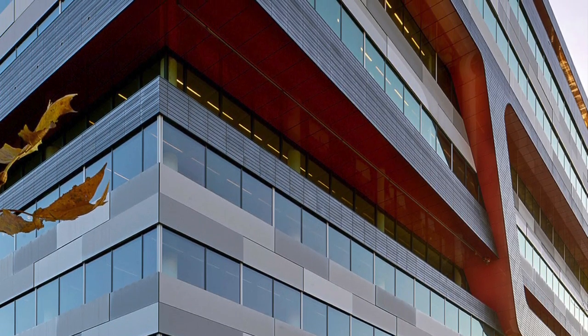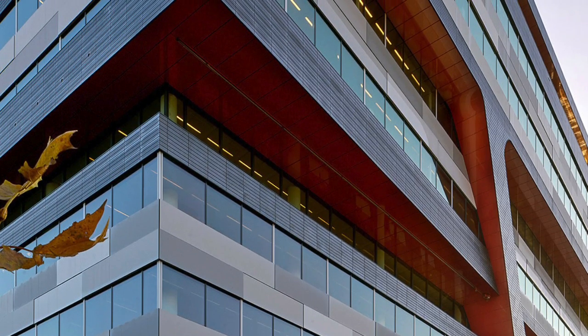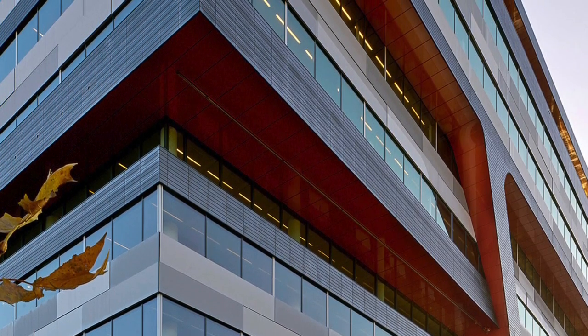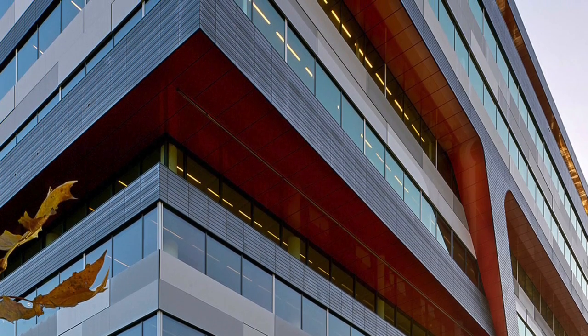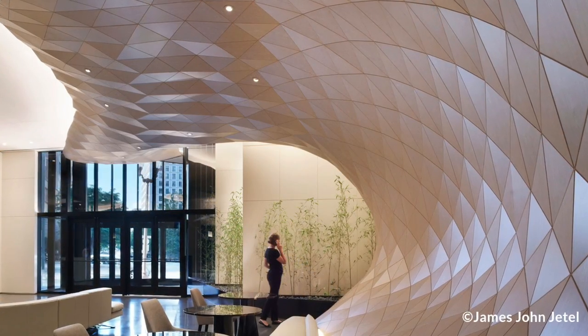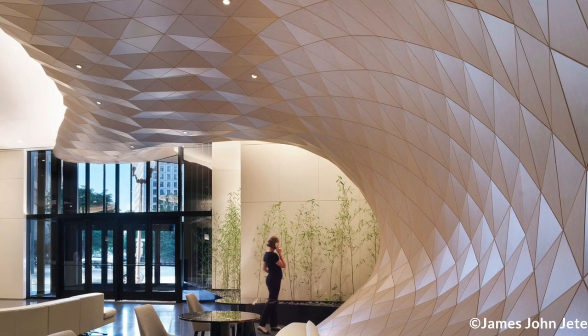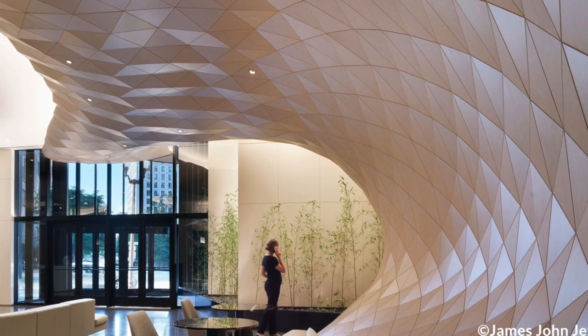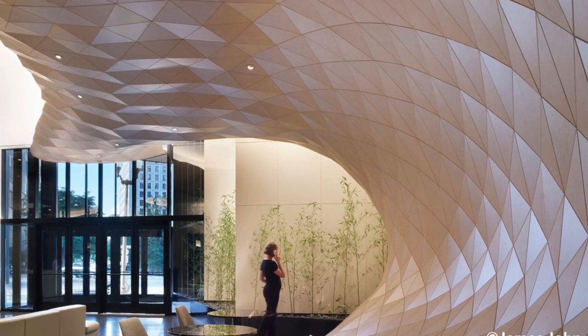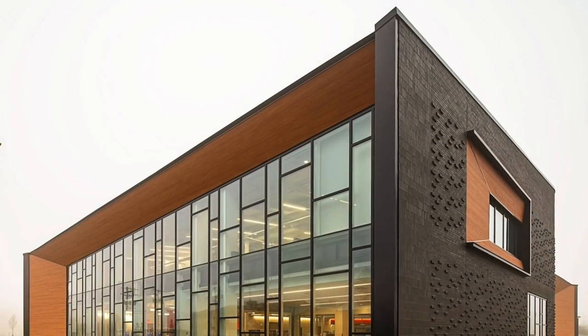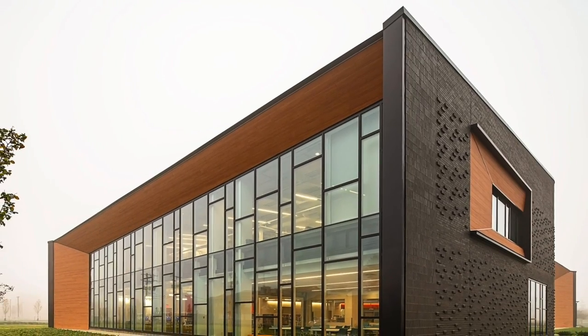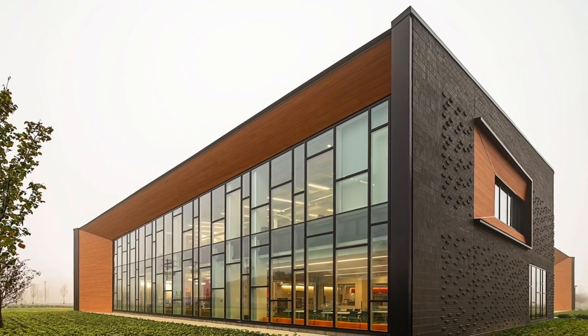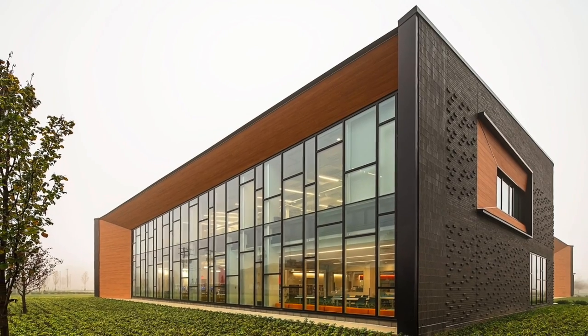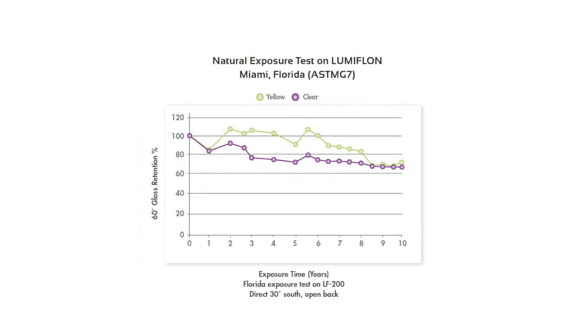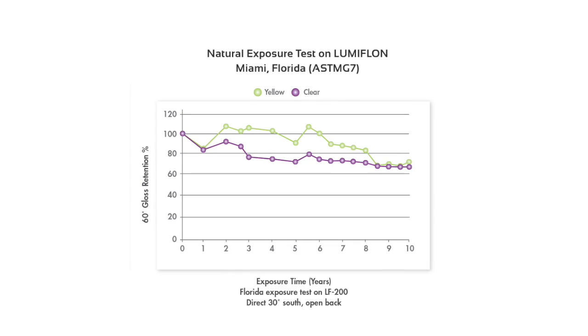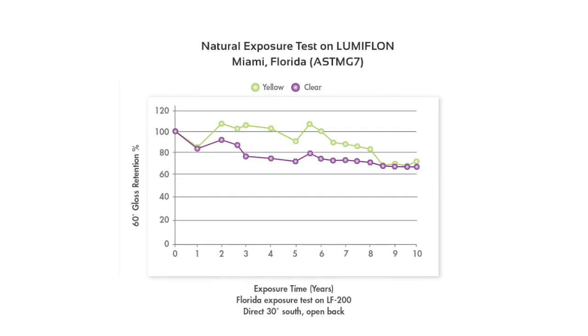And with Lumiflon's ability to resist UV degradation, corrosion, and the ill effects of chemical exposure, projects using Lumiflon continue looking good for years with little or no maintenance required. That means markedly less fading, discoloration, and chalking for the life of the coating, estimated at up to 60 years. FEVE resin technology has an unparalleled gloss range, which allows for brighter color palettes. With a long life cycle, projects with fluoropolymer technology have reduced recoating needs, which could be an expensive and disruptive potential cost.